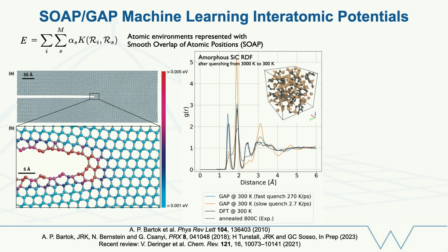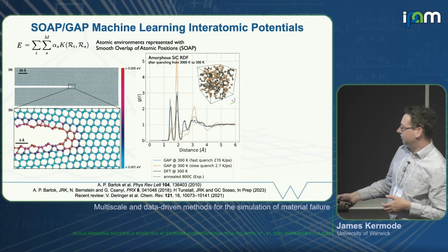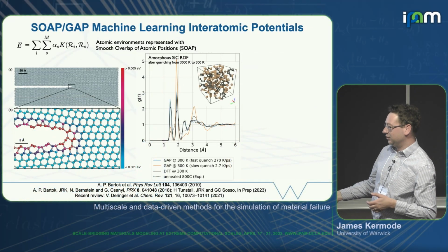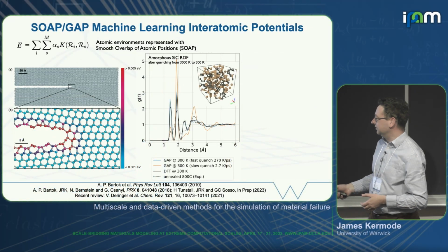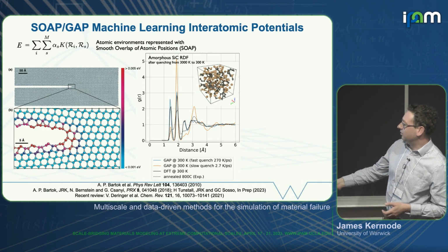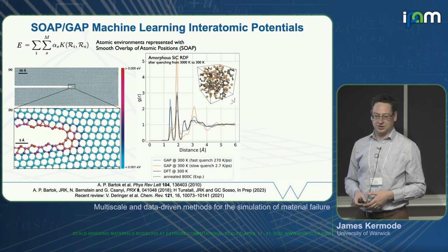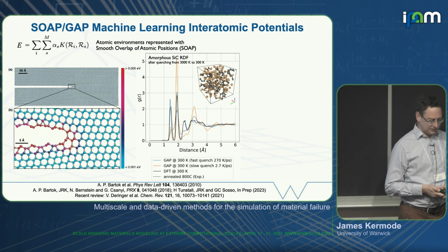However, once we have the machine learning model, we can afford to run it much more slowly, and we can cool down at a more realistic speed. It's still rather quick compared to experimental quench. And then we start to see a better agreement with the experimental structure. So it opens the door to doing new things with these models.